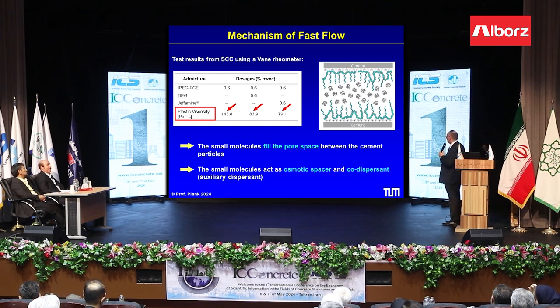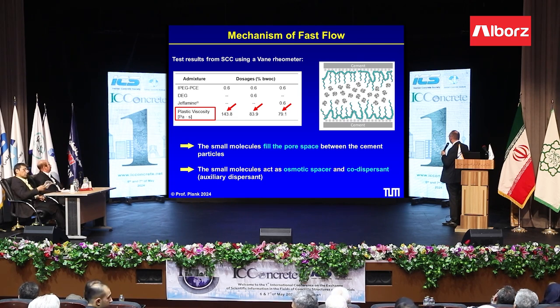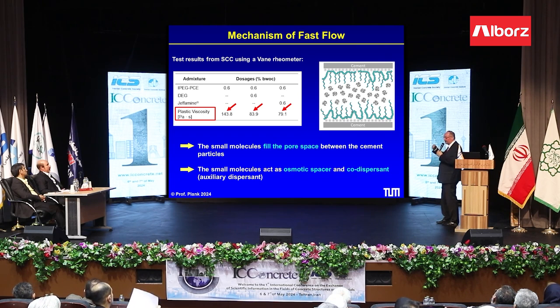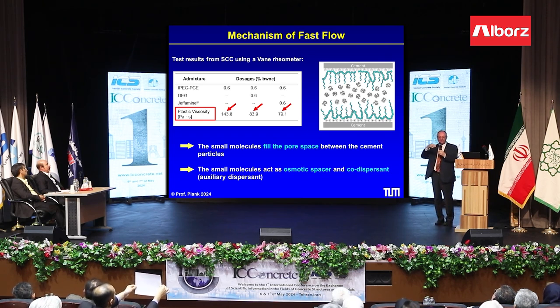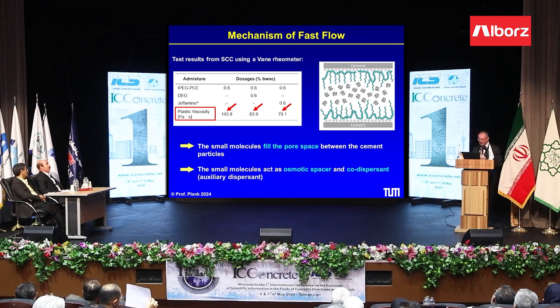And the reason is that they reduce the plastic viscosity of concrete. As you can see here, this is without such a glycol. And here we added diethylene glycol. Here we added Jeffamine. And then we reduce the plastic viscosity very much. The mechanism is that these alcohols, they do not adsorb on cement. They are in the pore solution, and they are a kind of steric spacer between the cement particles which hold the PCE. And so for osmotic reasons, the particles cannot come too close together, and then we have a dispersion effect.